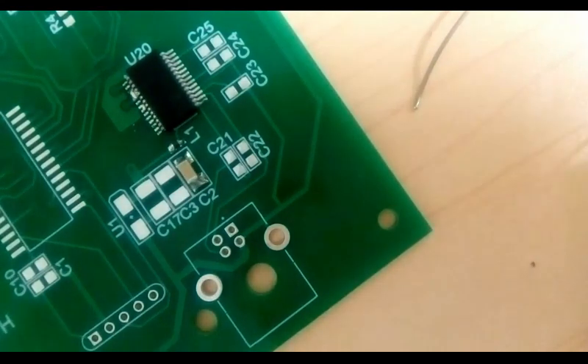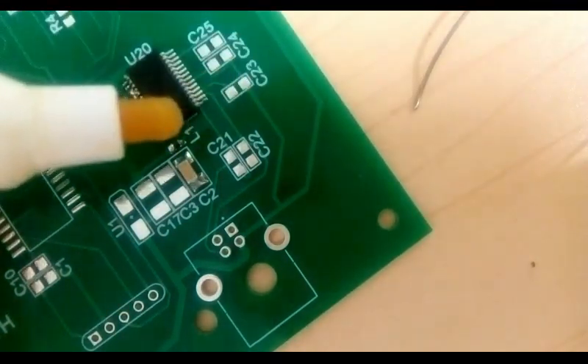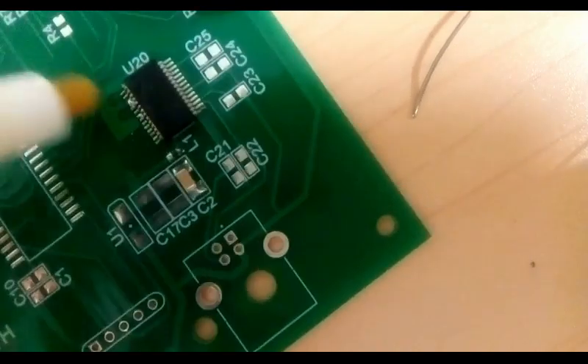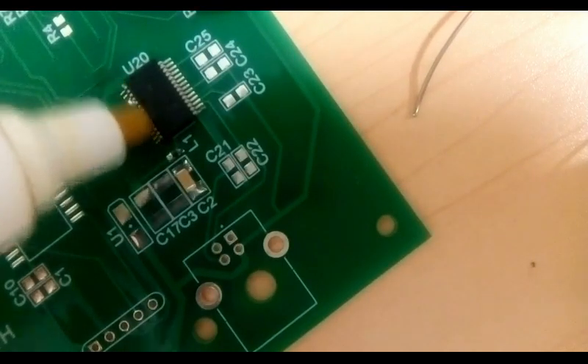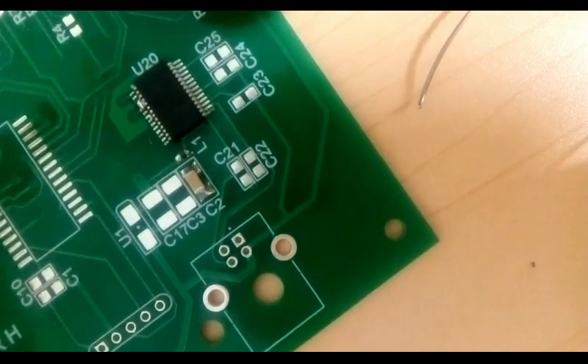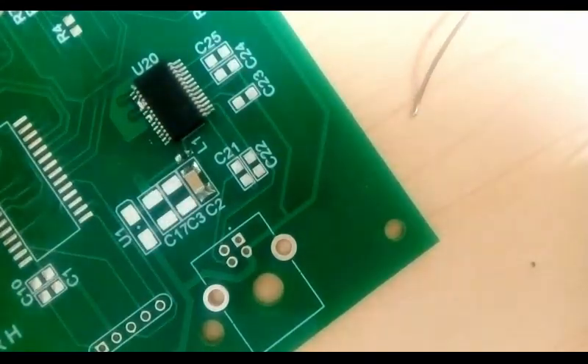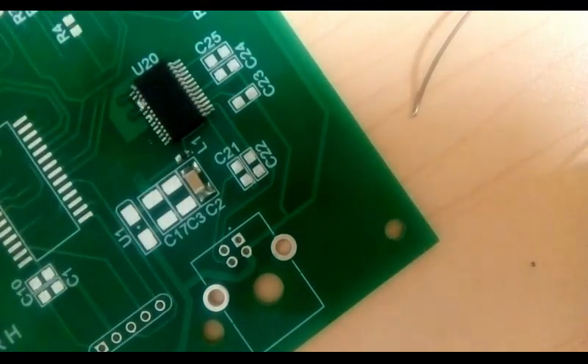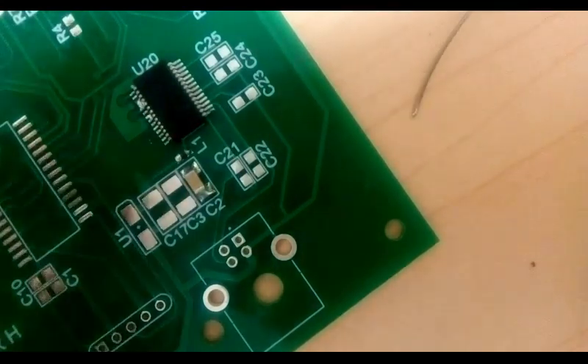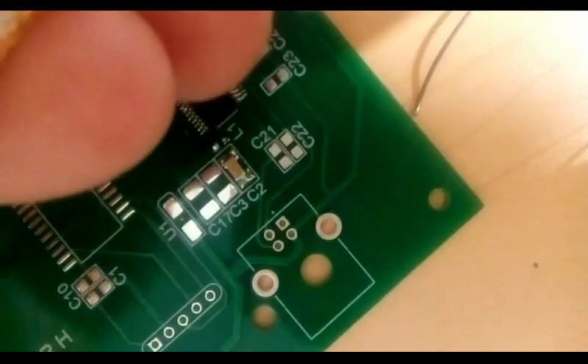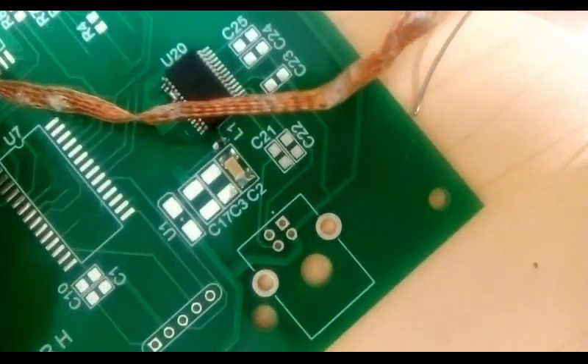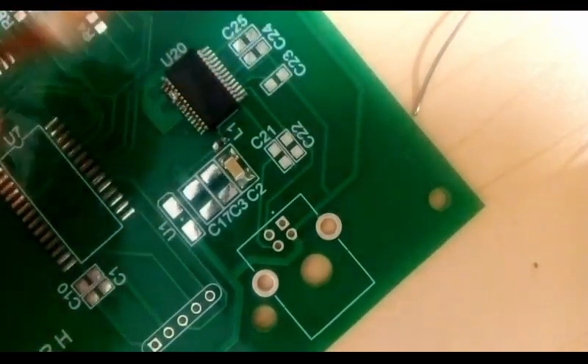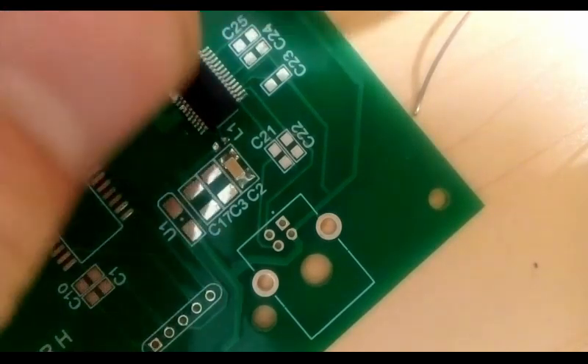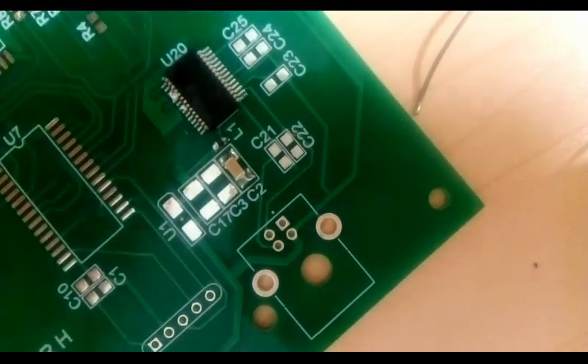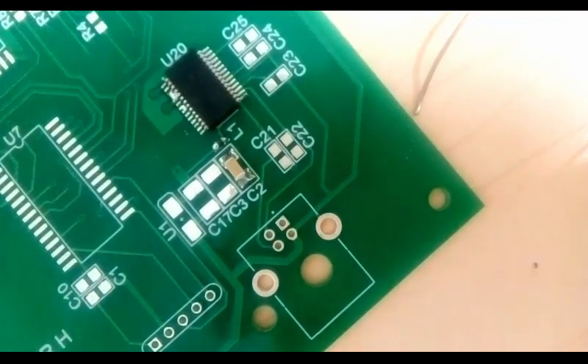Get rid of those bridges. We use our flux again. Liberal quantity of flux over the top of those. Sometimes flux itself is enough, but we're going to use solder wick. Solder wick is an absorbent copper wick with some chemicals impregnated in it that absorbs solder. And watch how this stuff works.